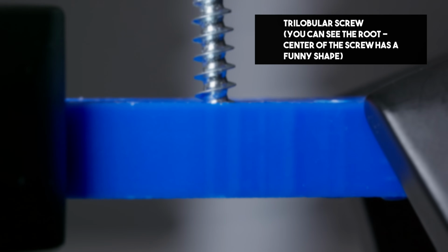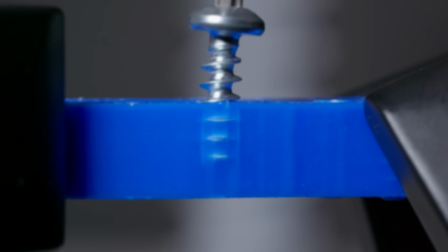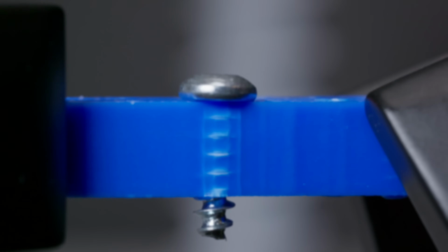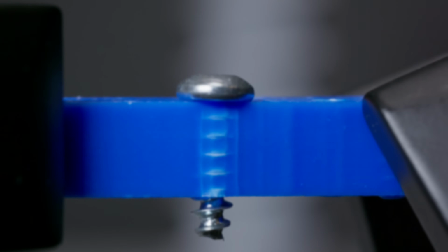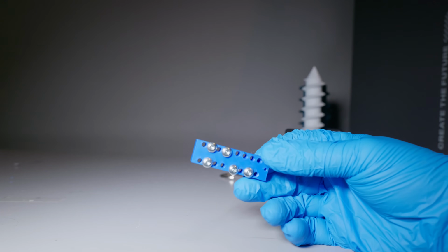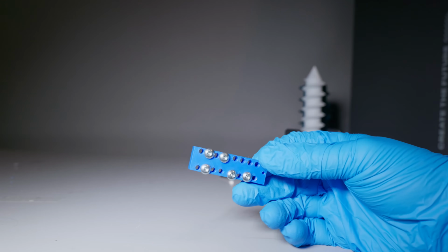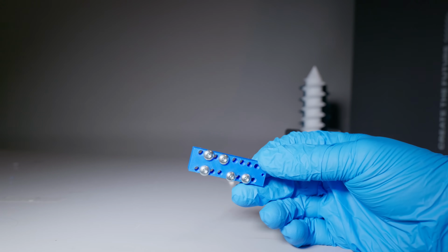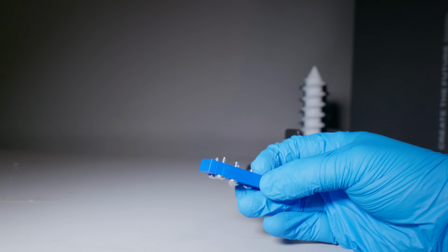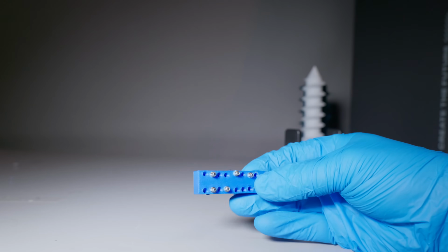You do get some marks on the edge of the part, but you shouldn't do this, in case it isn't already clear why. You can see those stress marks there on the outside of the part in the closest to the edge example. While it may not fail immediately, it probably will over time. PLA and some other plastics are very prone to creep, and so they will just take their time to fail.